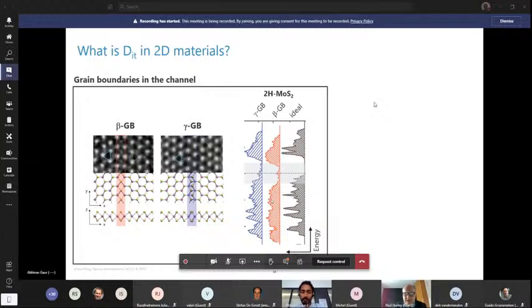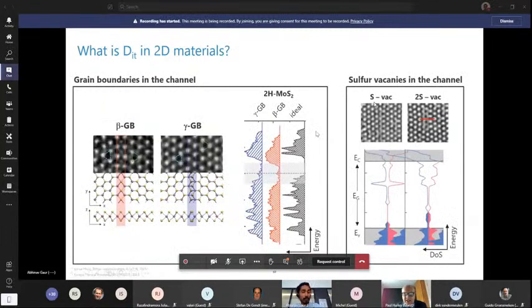Do you think this could be evidence that the defects are related closely to the interfacial layer between the 2D and the oxide? That is definitely one of the options, because I do mention that. But given the state of the channel right now, it is probably more likely that we are looking at these rather than the interfacial things. I think they would eventually start playing a role once we have high quality crystalline CVD grown 2D material. That's when they will start to play a bigger role. But even then, I've seen that point defects are also quite critical. Yes, point defects like sulfur vacancies and even double sulfur vacancies.